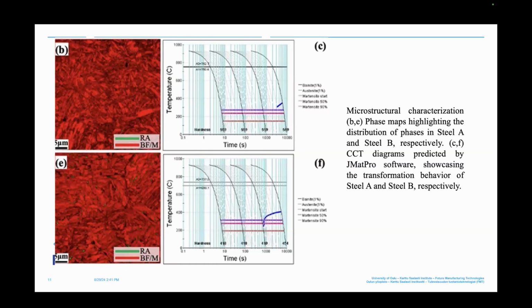And this one is the CCT diagram from JMatPro software to see the martensite transformation, Ms and Mf, and bainite. You can see that with high carbon, the Ms shifts to lower temperature. So okay, this is the theoretical CCT diagram, but actually we can now see the results.